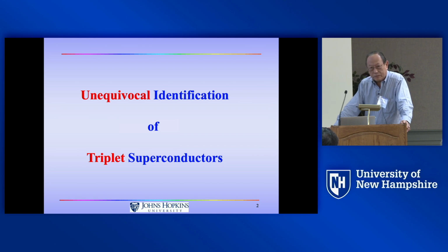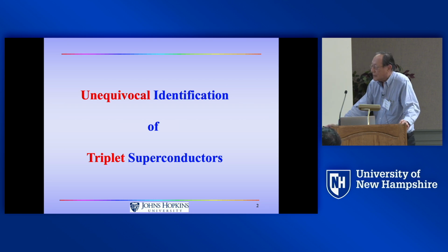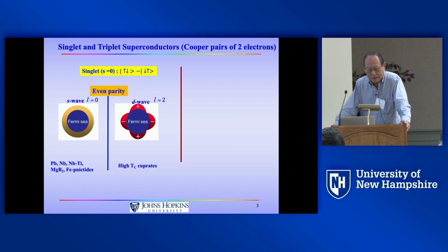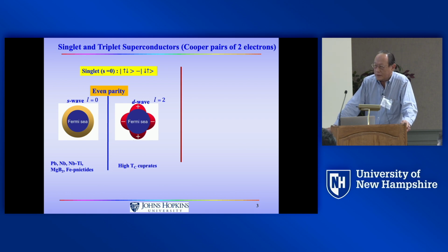Why are triplet superconductors important? The theorists told us that Majorana fermions live on triplet superconductors, which are important for fault-tolerant quantum computing. Superconductivity involves a Cooper pair of two electrons, and therefore they can form a singlet with spin 0. On the far left is the s-wave, the superconductor we're most familiar with, where the gap is constant and does not change sign. So you can do inversion and the value remains the same. High-Tc are d-wave, which also have even parity, but in this case the gap value changes, and if you turn 90 degrees, the gap value changes sign.